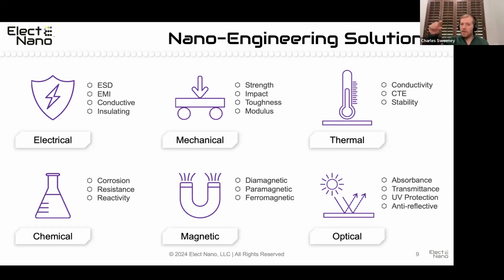Same thing with mechanical properties. We focus a lot on the interface around the tube. There's some situations where a direct covalent linkage, for instance with epoxies, you may pick a direct covalent linkage that maximizes stress transfer in more of a stiff way. That's going to maximize things like your stiffness and elastic modulus, but that may actually decrease the toughness of the system at high strain rates, because the ability to absorb energy in that very stiff bond doesn't allow energy to be released in a controlled manner.